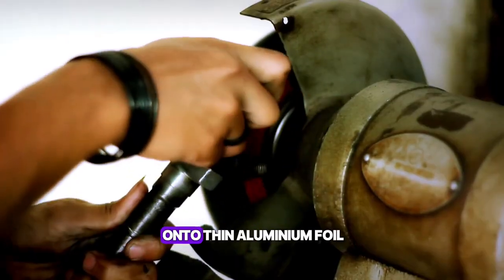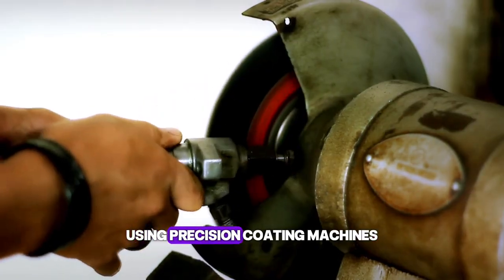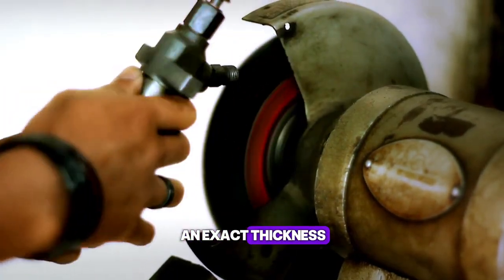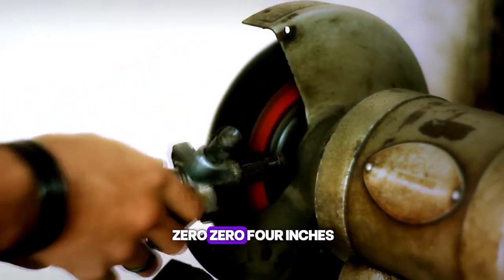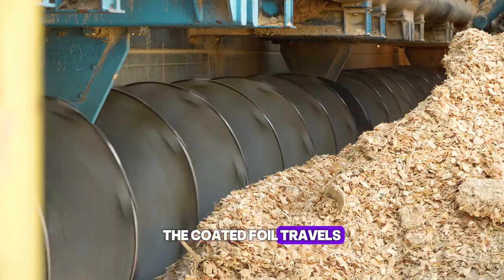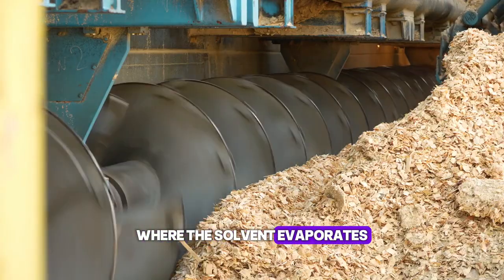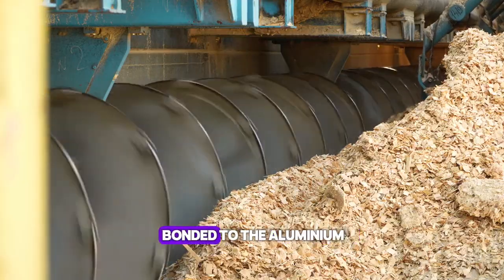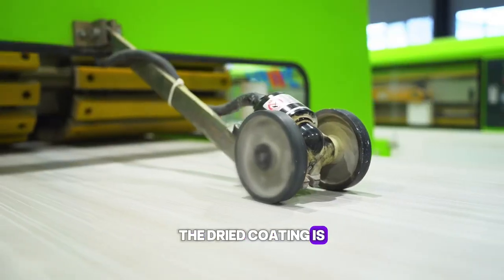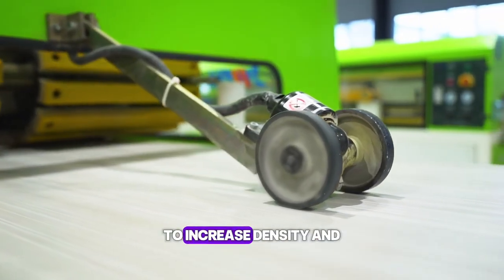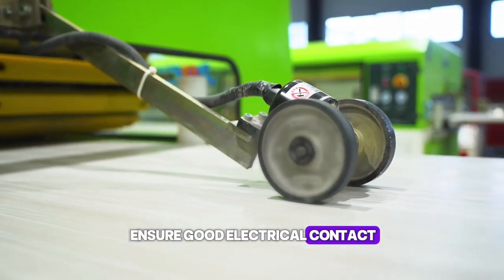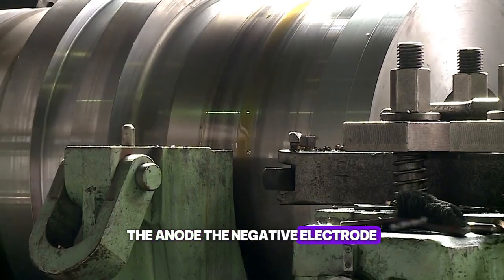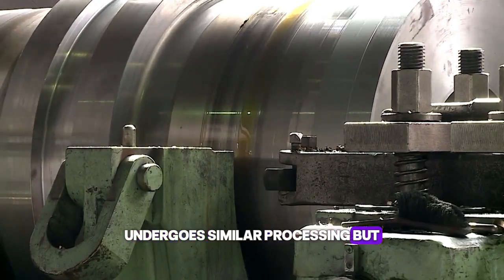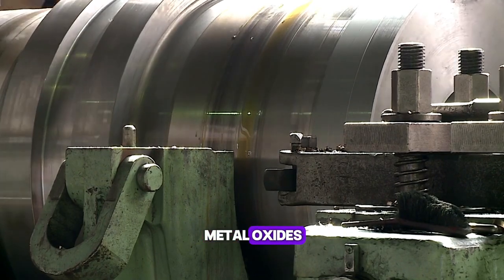The slurry is coated onto thin aluminum foil using precision coating machines that spread it to an exact thickness, typically less than 0.004 inches. The coated foil travels through long drying ovens where the solvent evaporates, leaving the active material bonded to the aluminum. The dried coating is then compressed by massive rollers to increase density and ensure good electrical contact. The anode, the negative electrode, undergoes similar processing but uses graphite instead of metal oxides.